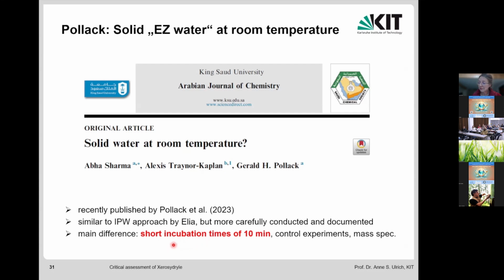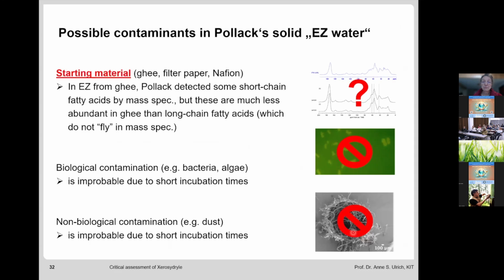Their paper was actually very carefully crafted. They used a very reproducible description of their method. They used very short incubation times of only 10 minutes as opposed to several weeks. So they carried out control experiments. They were very self-critical and even analyzed their solid water with mass spectrometry and said, well, maybe there's a few lipids in there. But let's see what we can find out by looking carefully at their data. So we can exclude, by all means, biological contamination.